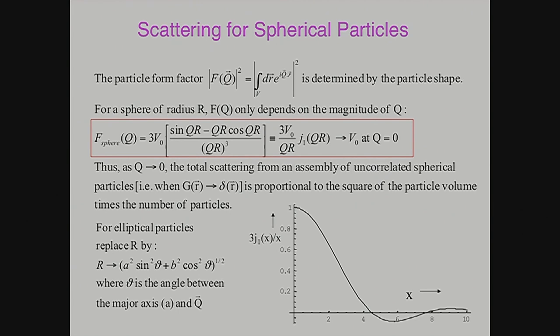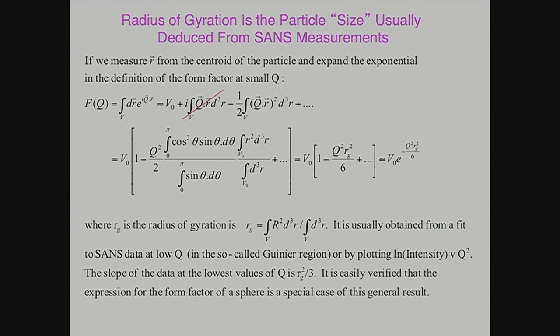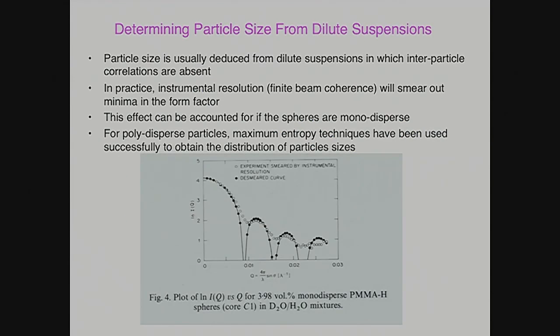Square this, you'll get something that comes down here, goes up here, and so on. And that's exactly this thing here. So this black curve is the form factor for spherical particles. The intensity goes to zero in these points here, and so in the log plot, it's diving down like this, it's sort of minus infinity here, in some sense. What you actually measure is these circular dots.